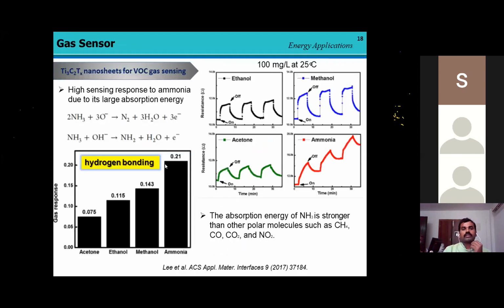Then not only in the supercapacitor application, a few groups in South Korea have also focused on sensor applications, where they have taken titanium carbide MXene for volatile organic compound gas sensing. Initially, the highly electron-donor molecules acetone, ethanol, methanol, and ammonia were taken for this study. They have observed on the MXene moiety. The MXene has functional groups of hydroxide and oxide on the edges as well as basal planes of MXene, which tend to form hydrogen bonding.